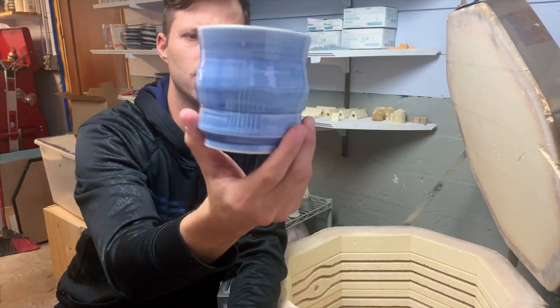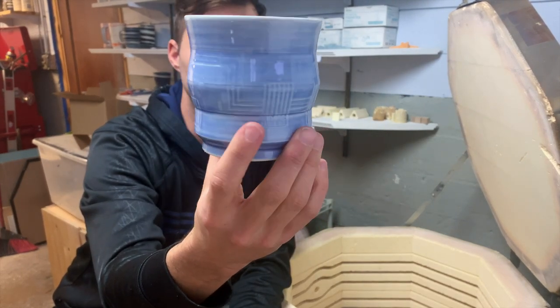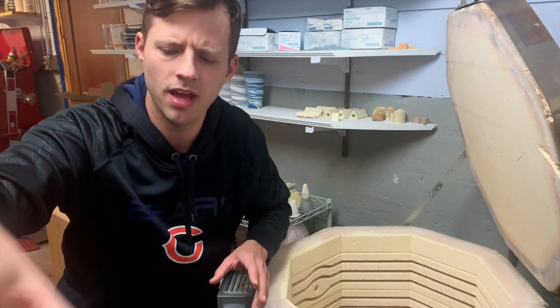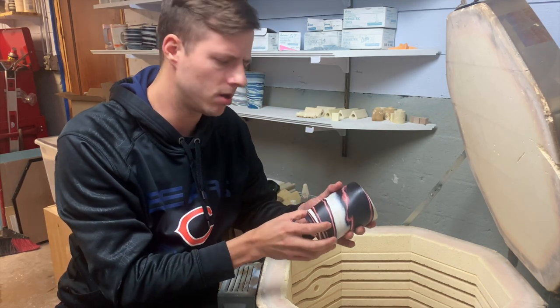Same base with — called Persian Blue. The AV base from Glazy.org. This is my new Cone 5 porcelain clay body — it might be Cone 6 now. I've added some silica to increase the firing range and added more kaolin instead of ball clay.